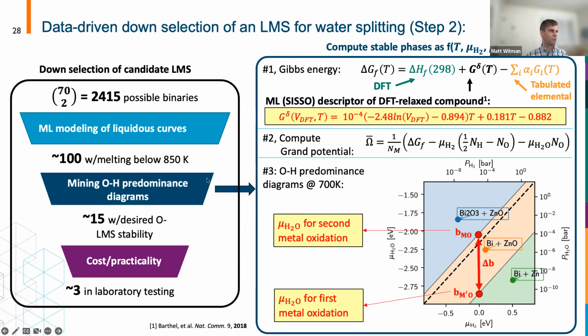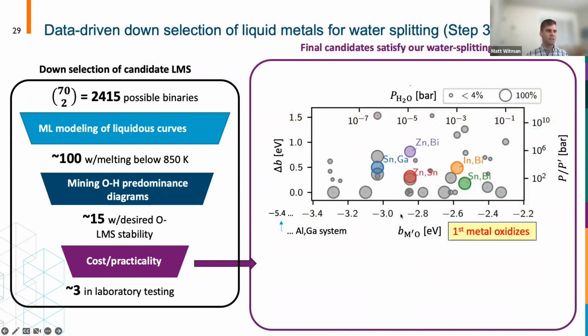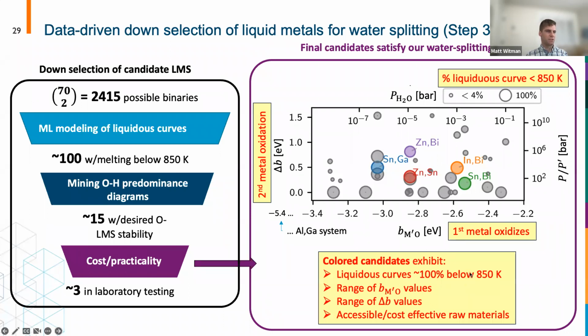So we can do that in high throughput for all the binaries. It's simple to compute, but we compute that for the 100 remaining candidates. And here I'm showing the chemical potential at which the first metal oxidizes and the delta at which the second metal oxidizes. And the bullet size here accounts for what percent of the liquidus curve is below that target temperature. So you can very quickly pick out just a few binary systems that would be the most experimentally promising to look at, because again, they melt below the target temperature, and they have a range of chemical potentials over which the first metal oxidizes, and non-zero values of this delta at which the second metal oxidizes. And furthermore, these are all accessible and cost-effective raw materials.